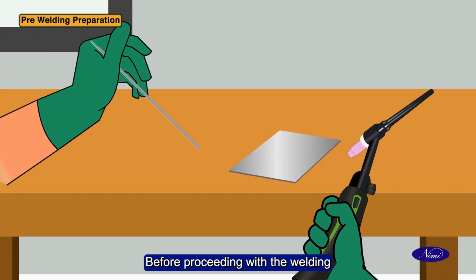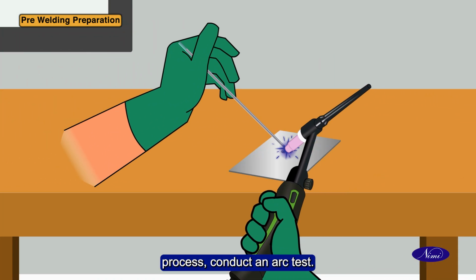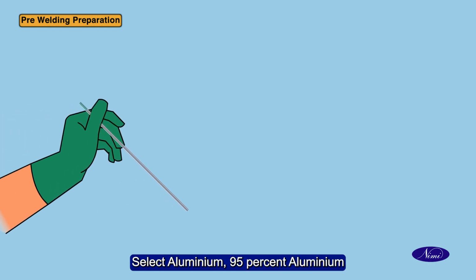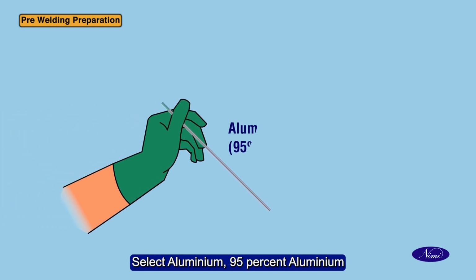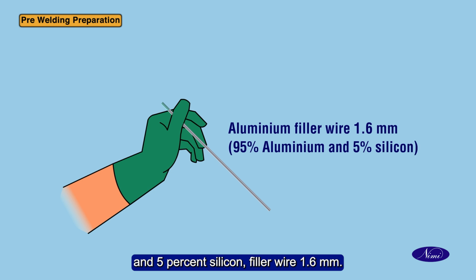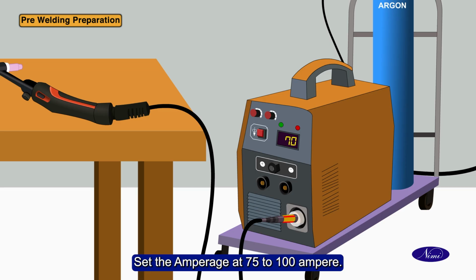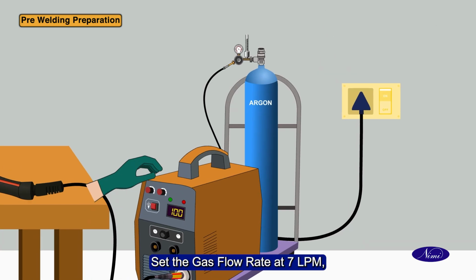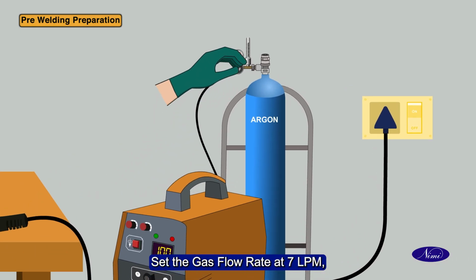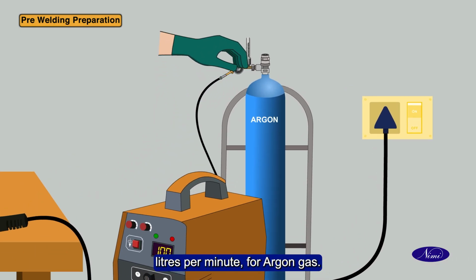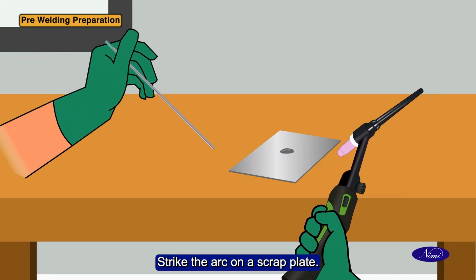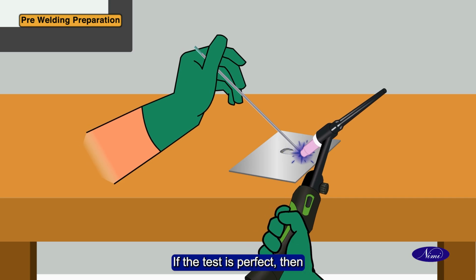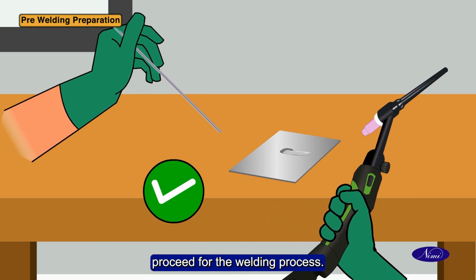Before proceeding with the welding process, conduct an arc test. Select aluminium filler wire, 95% aluminium and 5% silicon, 1.6 mm. Set the amperage at 75 to 100 ampere. Set the gas flow rate at 7 lpm, liters per minute, for argon gas. Strike the arc on a scrap plate. If the test is perfect, then proceed for the welding process.